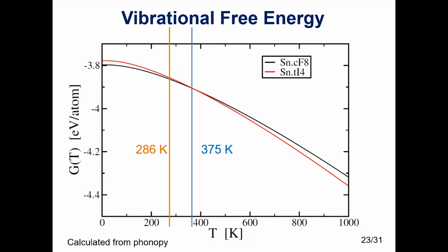And so let's stop and think whether maybe there's a reason for that. Well, a possible reason would be the electronic free energy. The electronic free energy arises from the smearing of the Fermi surface. So here we have the Fermi occupation function that gives the occupation probability for a single electron state at energy E relative to the chemical potential, which is pretty close to the Fermi energy.